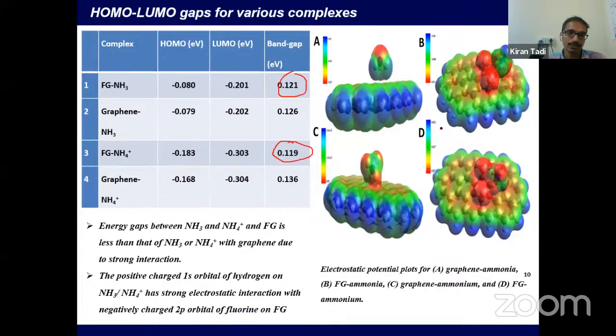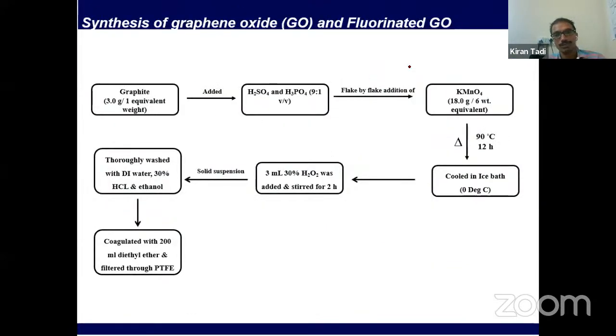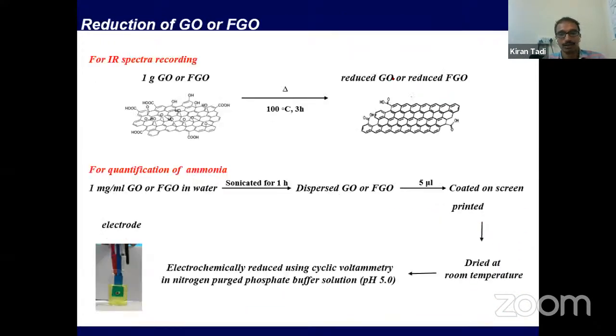So once we did this theoretical calculation, we synthesized the graphene oxide by the improved methods of graphene oxide synthesis. Once we synthesized this graphene oxide, we reduced it both without any reducing agent and in the presence of a reducing agent. One method was just heating the graphene oxide at 100 degrees centigrade for 3 hours.